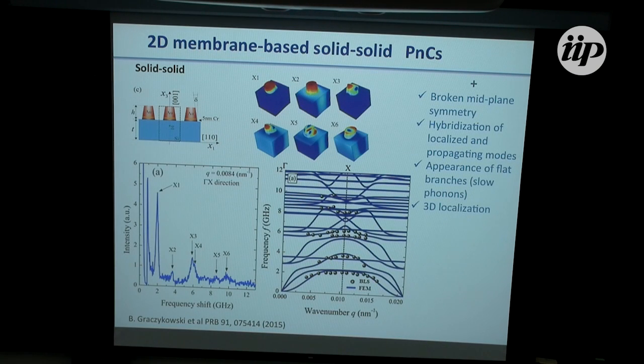The solid-solid phononic crystal, by contrast, again, this is our workhorse, Brillouin light scattering. We pick up all the relevant scattering peaks along the gamma X direction. And you can see there is a serious difference in the dispersion relation here. So we basically have put resonators that absorbed energy and slow down the propagation of waves. So the hybridization has these two impacts on it. So instead of having a broken mid-plane symmetry, that is gone, because now we have added something on one part,